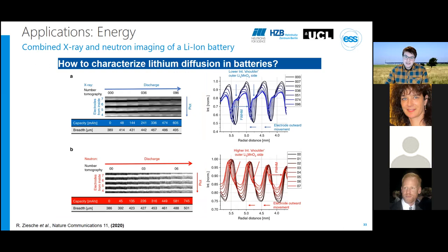For X-rays, we don't have really contrast for the lithium, but we see very clearly the expansion of the manganese oxide electrode during the discharging, which is depicted on the Y-axis here for seven different discharge states. For neutrons, we have a strong contrast from lithium because it absorbs neutrons rather strongly. For instance, you can see the diffusion of lithium inside the manganese oxide electrode. This example, I think, illustrates that the complementarity of the two tomographies is capable of providing a much more complete picture of the processes inside a battery under operation than if only one imaging modality would be used.